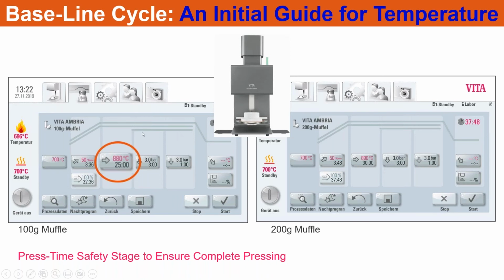air-driven press furnace, and it may not be adequate to press it. So what VITA's done is, in their cycles, they've added maybe an additional press time. The way our furnaces operate is that after you have the hold time, and it begins to go into the press process, we set it up so that you have a 3-minute press time. In those 3 minutes, if the piston feels that there's no longer any downward movement, it will shift from this first press segment to the secondary press, and if it still continues to feel that back pressure, no movement within the piston, it will end.